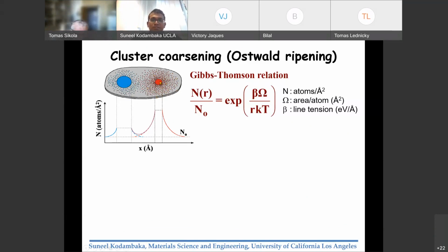And the rationale behind this phenomena is that the vapor pressure associated with a given size of a cluster or a three-dimensional object is exponentially related to its curvature. And it's mathematically given by the Gibbs-Thomson relation, where the atom concentration N associated with a cluster of radius R is exponentially related to the step energy and the curvature of the island. Okay, in this form here, this is assuming that these are circles, and that's why the curvature is written as 1 over R. But to be in the strictest form, this would be written as curvature. Okay? And N0 would correspond to the equilibrium atom concentration associated with a straight step.